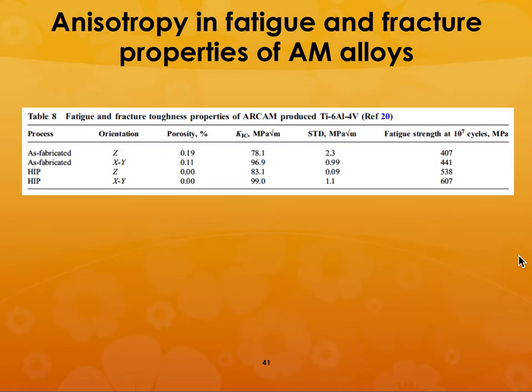So again, the fatigue properties are going to be different in the as fabricated and the hipped samples, or hot isostatic press samples. So you can see that by doing hot isostatic processing, you're going to be taking away some of the subsurface flaws, and that clearly leads to an improvement in the fatigue properties and the mechanical properties.